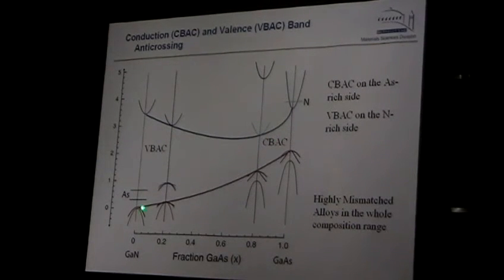Now, on this side, we have gallium nitride. Gallium nitride has a very large gap, 3.4 electron volts. Now we take some of the nitrogen, remove it, and put our arsenic in. What does arsenic do in gallium nitride, right? In fact, arsenic forms a level above the valence band, and this is a fully occupied, so-called donor level. Now when you add more and more arsenic, in fact the same happens. The arsenic starts to interact with the valence band and forms a new band. And now the gap is measured from here to the conduction band, and of course there is an immediate drastic reduction in the band gap.